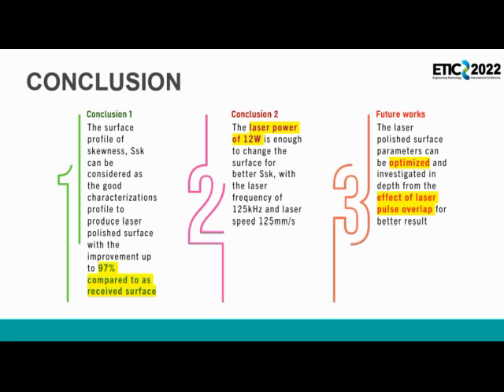Number 1, the surface profile of Ssk can be considered as a good characterization profile to produce laser polished surface with an improvement up to 97% compared to the as received surface. Conclusion 2, the laser power of 12 watt is enough to change the surface for better Ssk with the laser frequency of 125 kHz and laser speed 125 mm/s. Lastly, for future works, the laser polish surface parameters can be optimized and investigated in depth from the effect of laser pulse overlap for better results.